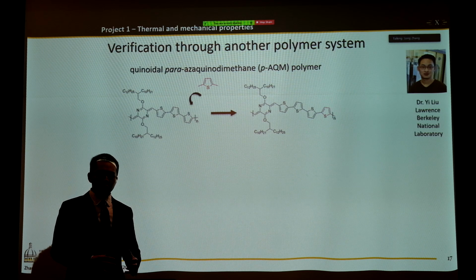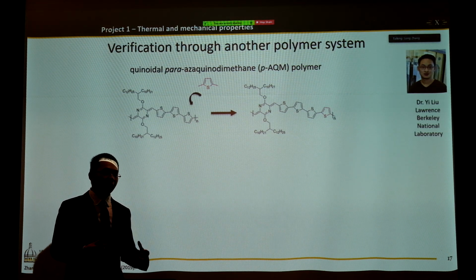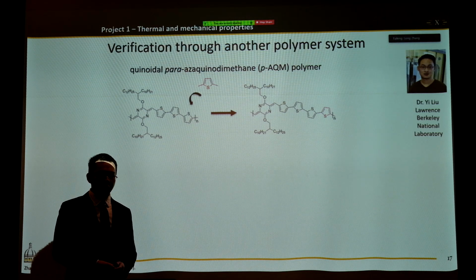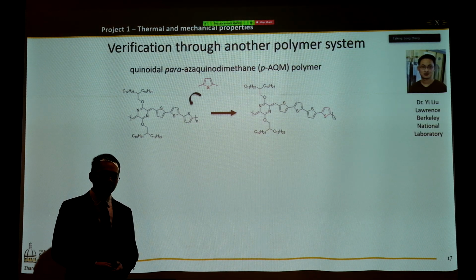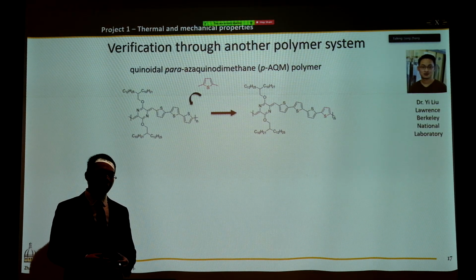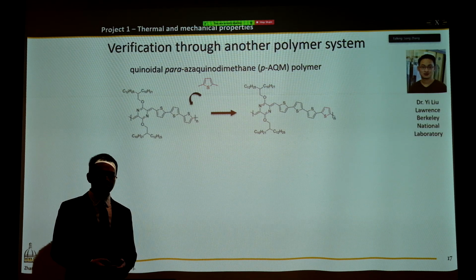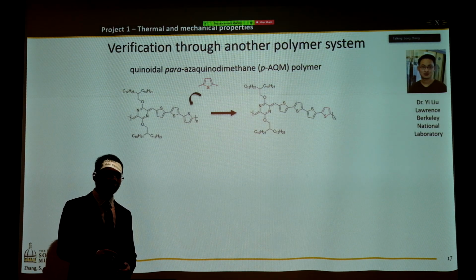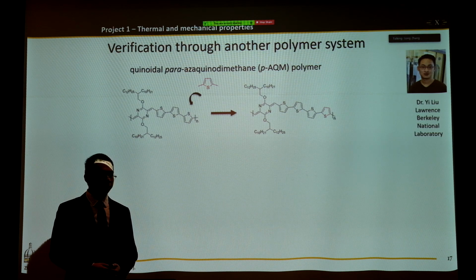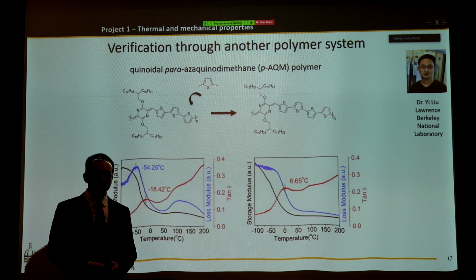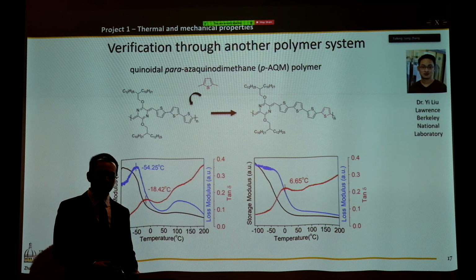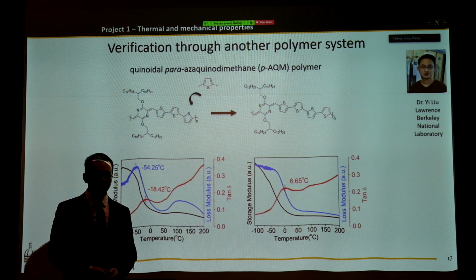Okay, now to verify the improved glass transition temperature we observed, we use another conjugated polymer system. We collaborated with Dr. Liu at LBNL, where we use a similar concept by introducing one thiophene unit into this PAQM polymer. And we find the Tg can be efficiently increased all the way from -18 to 6 Celsius degrees. Okay, so how do we understand it?